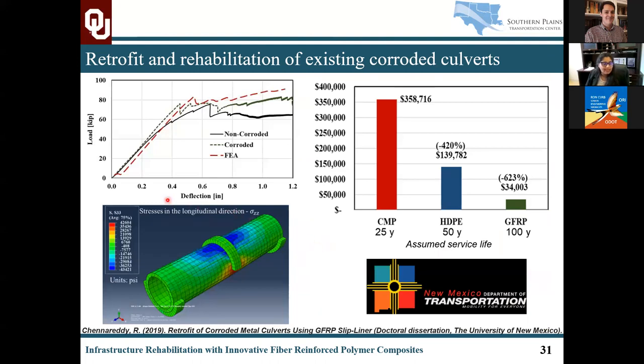So we do see that both computational and experimental analysis have shown that corroded and non-corroded are really performing on par with each other with this retrofit using GFRP slip liners. We have different models that can be used to study what kind of bond capabilities with the grout and with the existing corroded steel sections can be offered with the FRP.